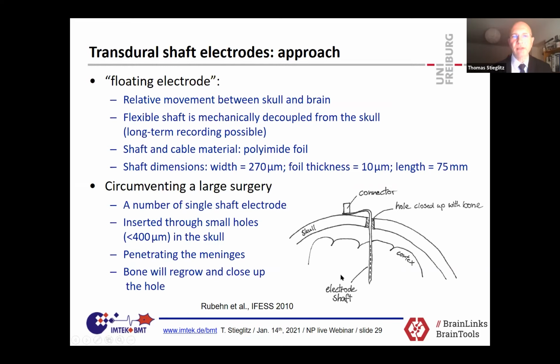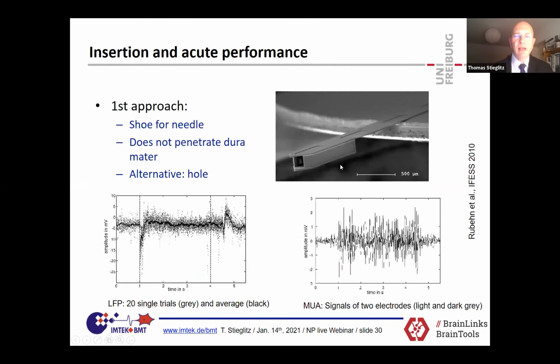We did that again with our technology, and we had some crazy but a bit stupid ideas of a horseshoe that we could use to put a guide wire in and then push the horseshoe with a small flexible probe inside the brain. And it turned out, as you can see here, that the horseshoe is so large that it will destroy everything, and you don't get it through the dura and it will not work. So we had to play some tricks to get at least some signals here.